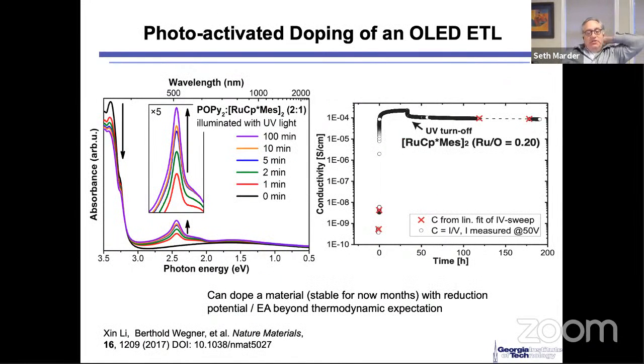So in this slide, what we show is what happens to the spectra as we photoexcite. Don't worry about this curvature here. This curvature here is basically an artifact of the fact that we're working on the thin film of an electrode. Okay, you see this band growing in. This band is the radical anion of POPY2. How do we know that? Because we generated it by another route, okay? So that's the radical anion, and it grows in with time.